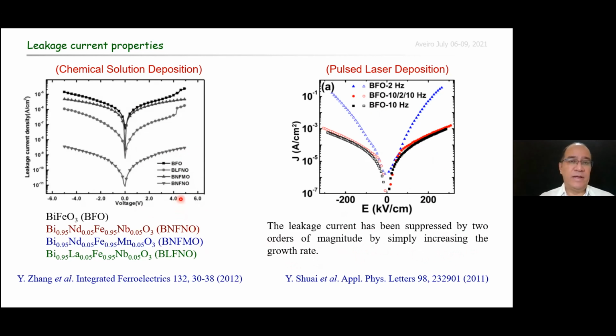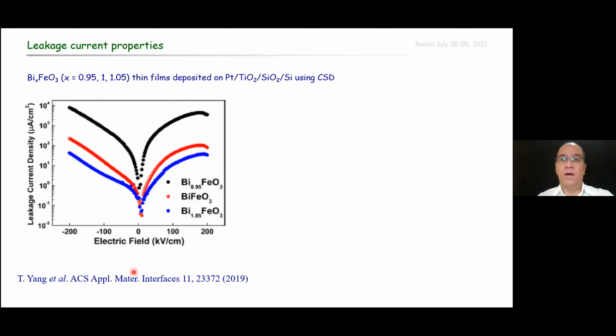On the other hand, in the BFO film prepared by chemical route, we observed that leakage current was suppressed by at least 5 orders of magnitude, introducing dopants such as lanthanum and niobium. On the other hand, changes in the bismuth stoichiometry also lead to BFO films with different leakage currents, as observed in this figure from a recent work of T. Yang et al., published just 2 years ago.